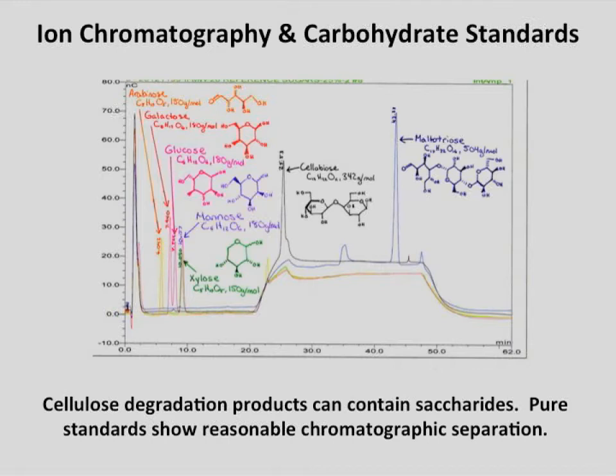We start with a low concentration of sodium hydroxide as our eluent, and then to clean the column out before the next injection, we increase that concentration so the signal of the detector goes up. Interestingly, that's when we see cellobiose, the disaccharide, and the trisaccharide - they come out way late in this process.